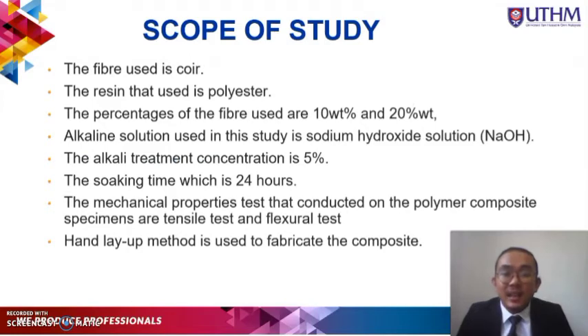In this study, the scope is: the fiber used is coir. Next, the resin used is polyester. The percentages of the fiber used are 10% and 20%. The alkali solution used in this study is sodium hydroxide, which is 5% concentration, with a constant soaking time of 24 hours. The mechanical properties tests conducted on the polymer composite specimens are tensile tests and flexural tests. In this project, the hand layup method is used to fabricate this composite.